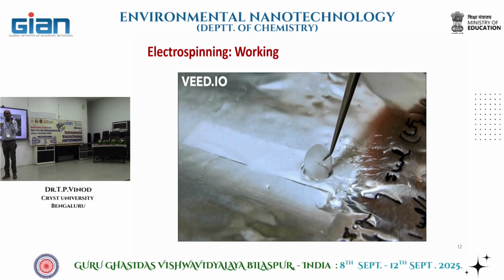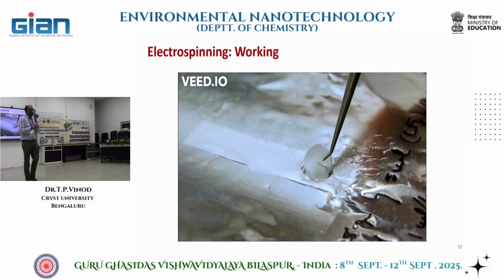And getting the polymer solution to spin as fiber is a very challenging task. Not every polymer will spin. You need to have the right combination of polymer and solvent. You need to have the right voltage. You need to have the right distance between the tip and the collector. Many things you need to customize. Even then, some polymers are not spinnable. In that case, they will undergo something called electrospraying. Electrospray means it gets sprayed, and then you get deposition of nanoparticles.